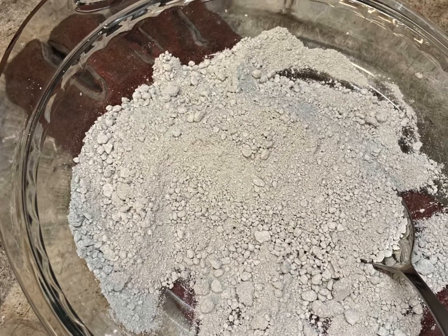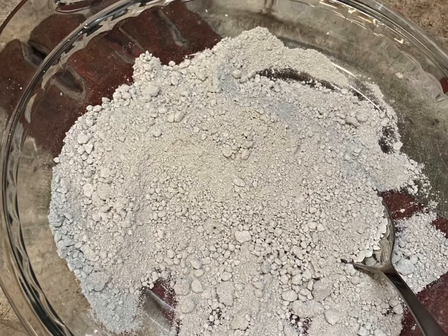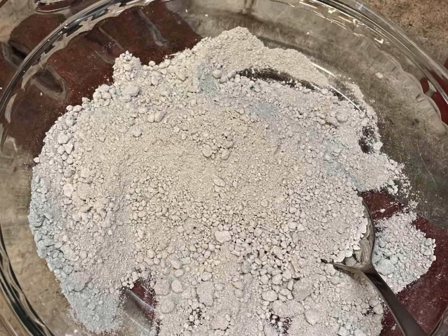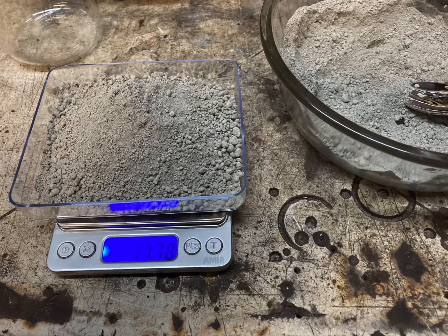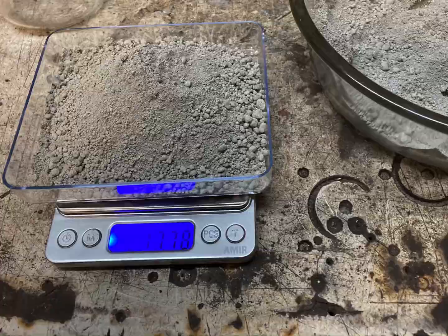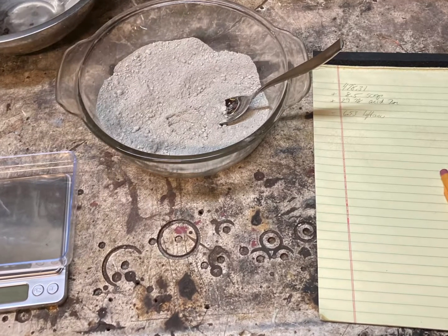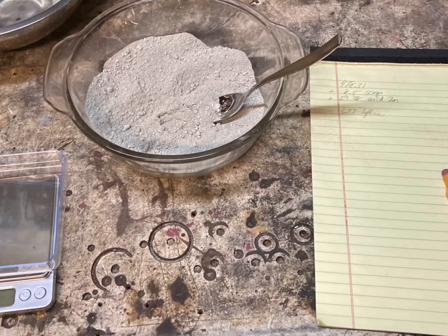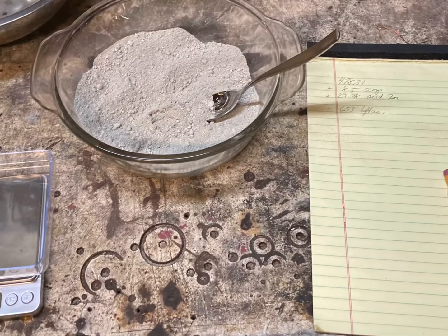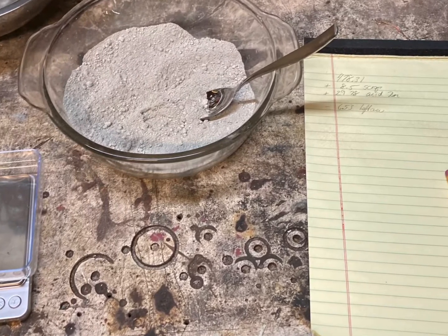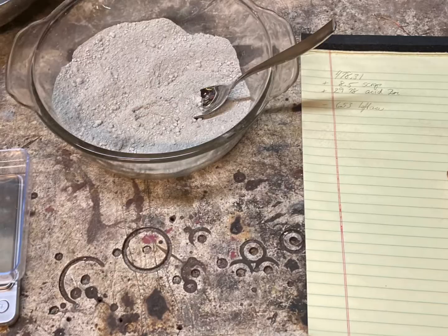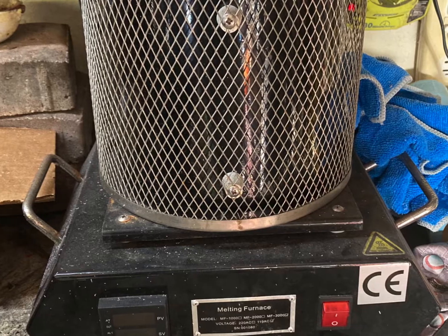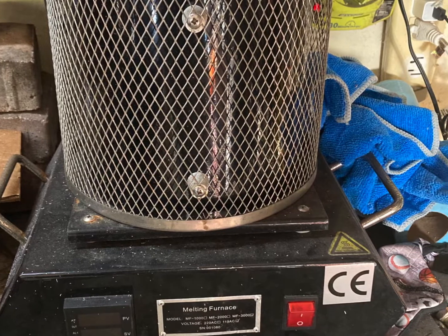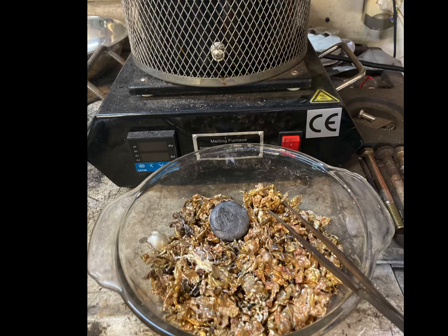This is the first chance you get to see what kind of yield you produced. If you can get around 90 to 91%, you're doing pretty good. You can melt down just the cement, but it's really difficult when it's this dry because it just blows away when you try to put a torch to it. So I always like to melt mine down in the furnace and then pour it into shot. Nothing goes perfect, and in this circumstance, I ended up contaminating the shot.